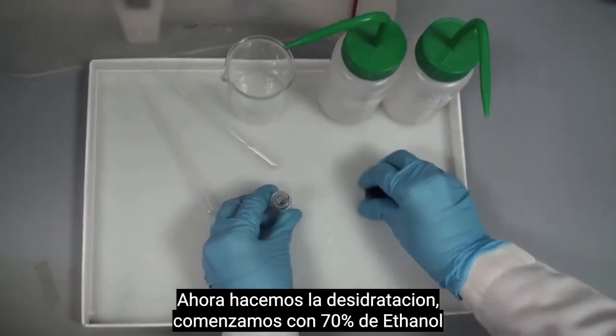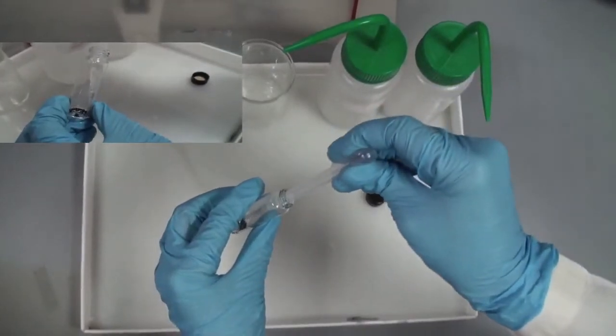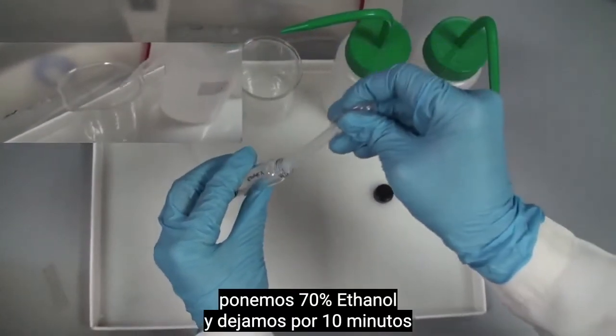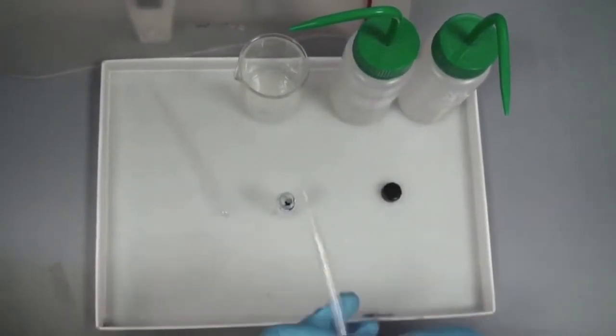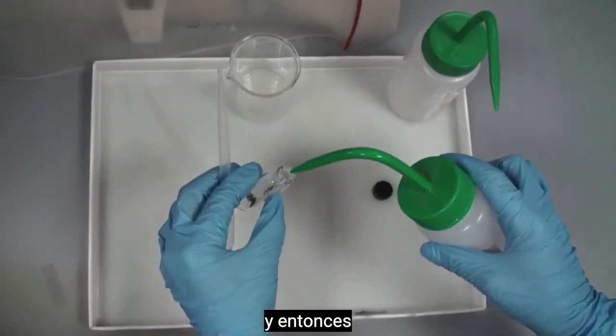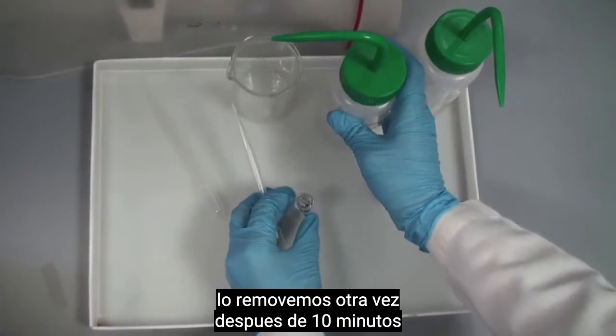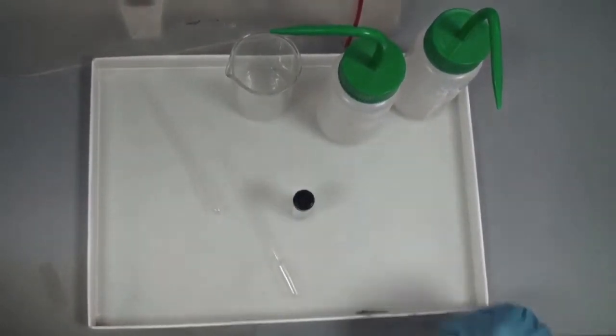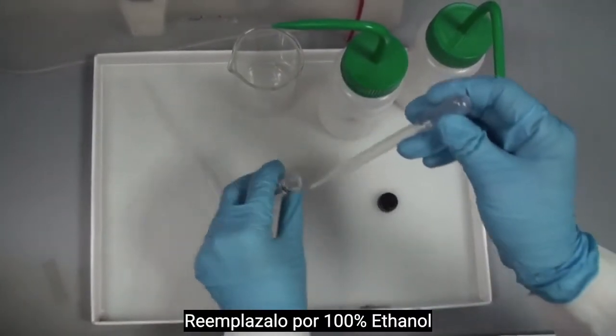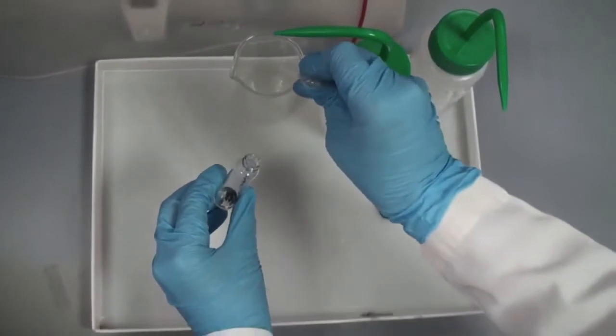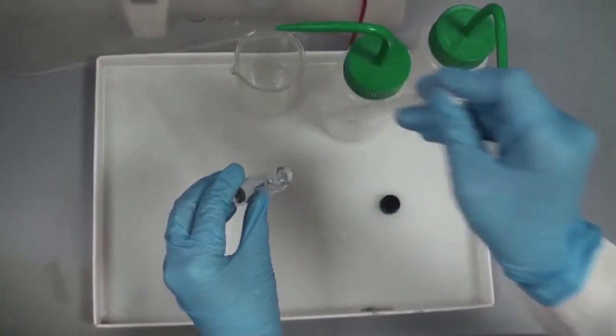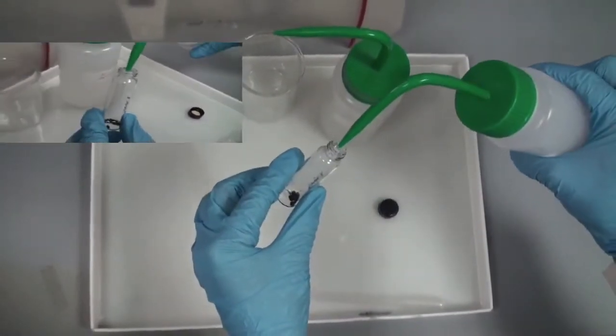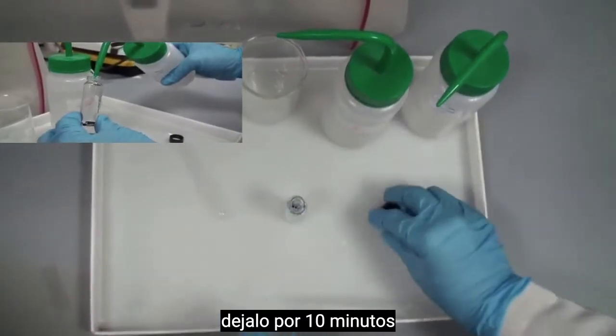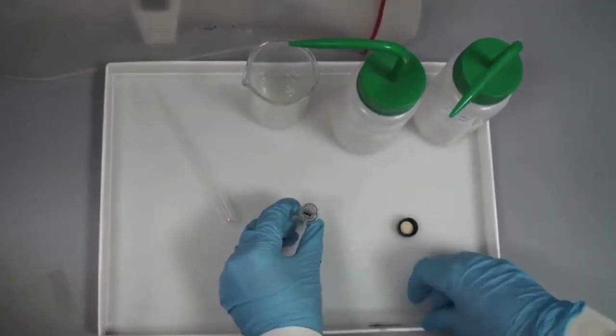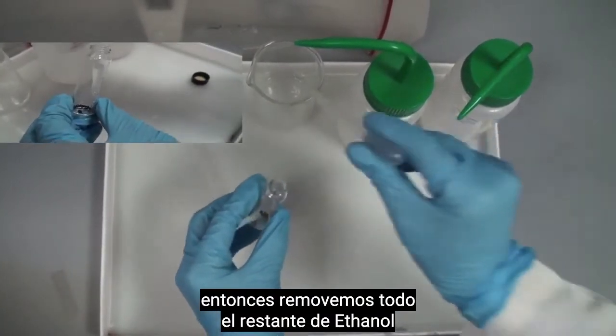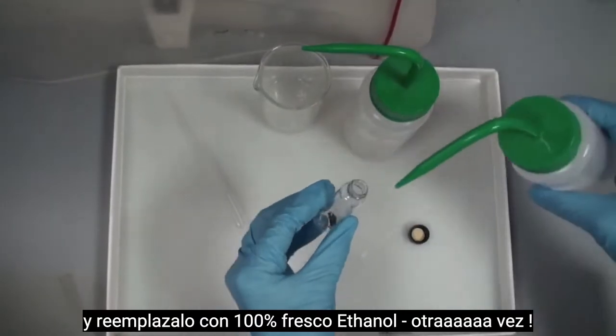Now we will do the dehydration step. We will start with 70% ethanol. First we remove the PBS, put 70% ethanol, leave it for 10 minutes, and then remove it again after the 10 minutes. Replace it with 100% ethanol. Leave it for 10 minutes and repeat the final step again. So we remove the 100% ethanol and replace it with fresh 100% ethanol again.